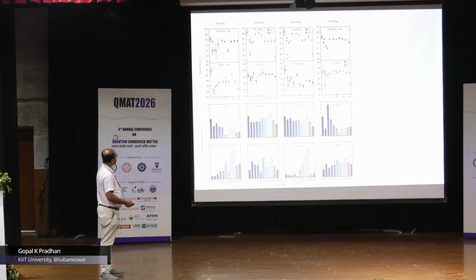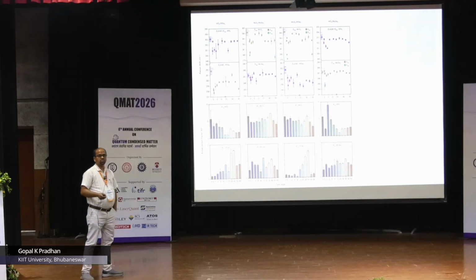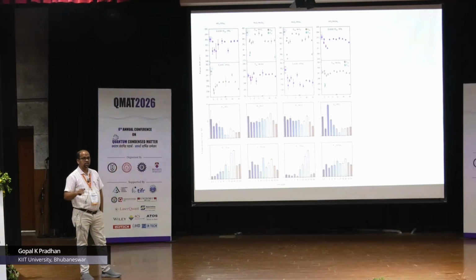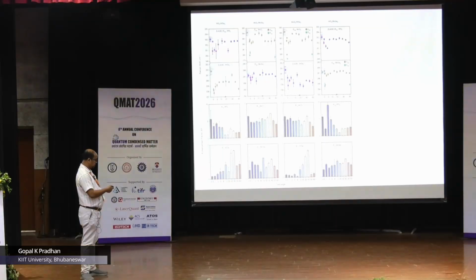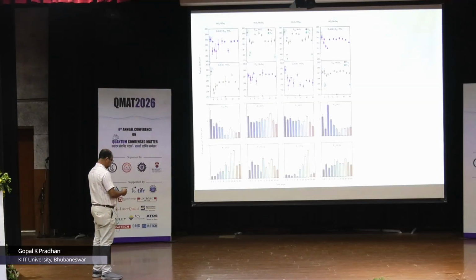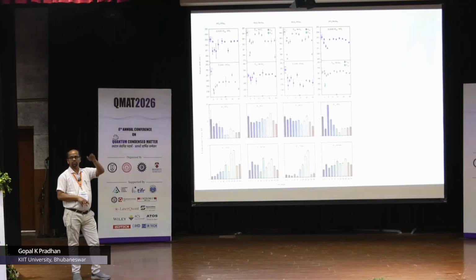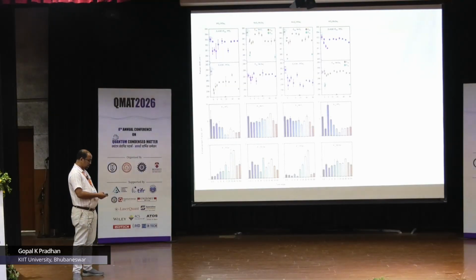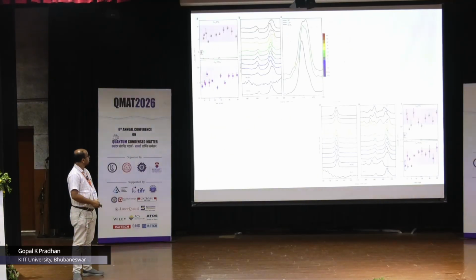Okay, something is not right here. You can actually do a lot of analysis using Raman of different peaks, A1g, E2g, etc., and see how their Raman shift changes as you change this twist angle. And this is an analysis where you can identify which modes have maximum enhancement in their intensity and frequency shift, and then you can correlate with certain properties, let us say the mechanical properties or the thermal properties, and this is what gives you a lot of interesting aspects.